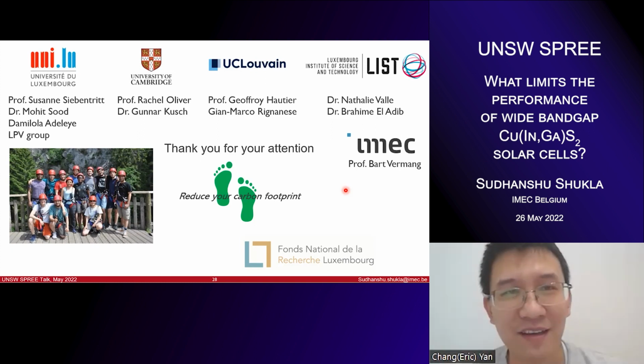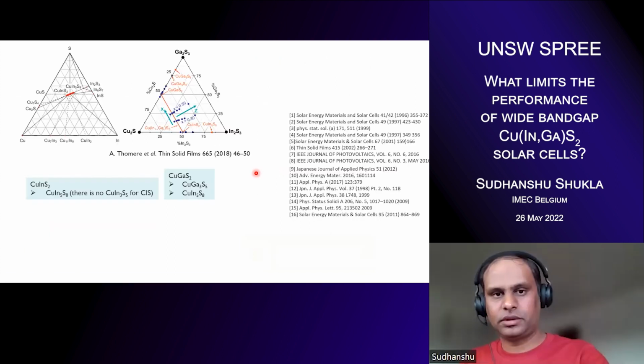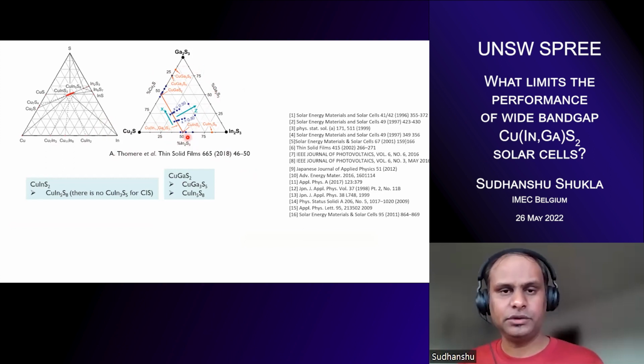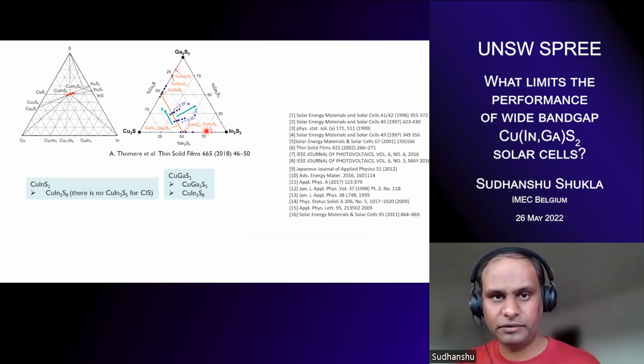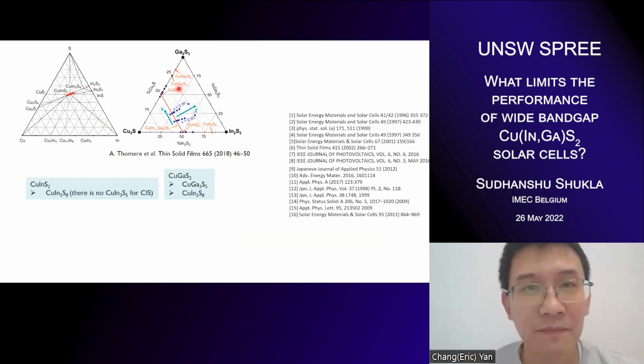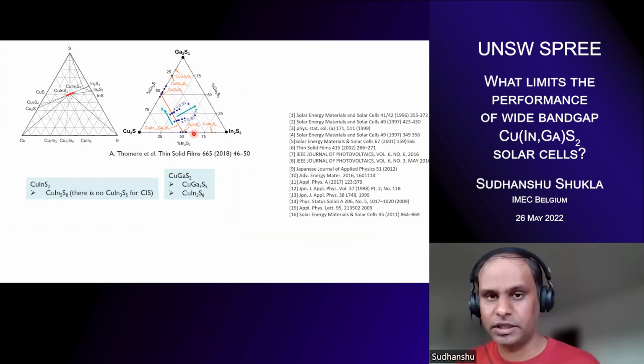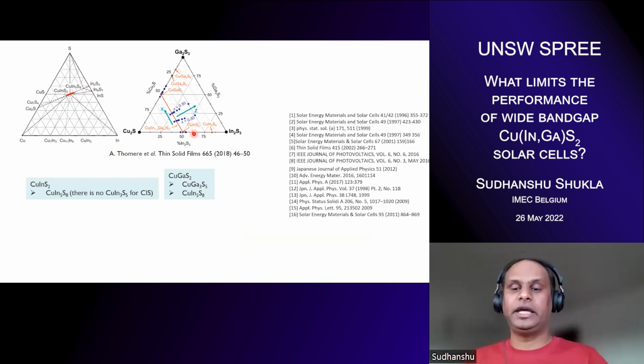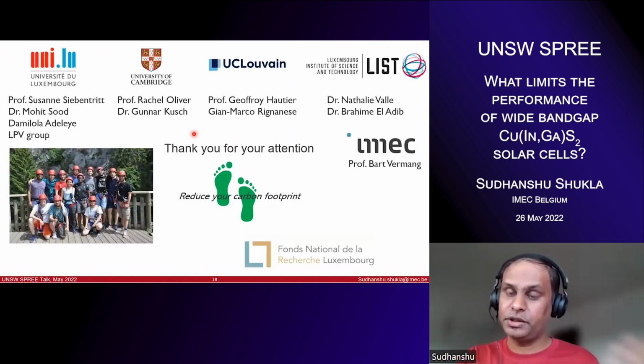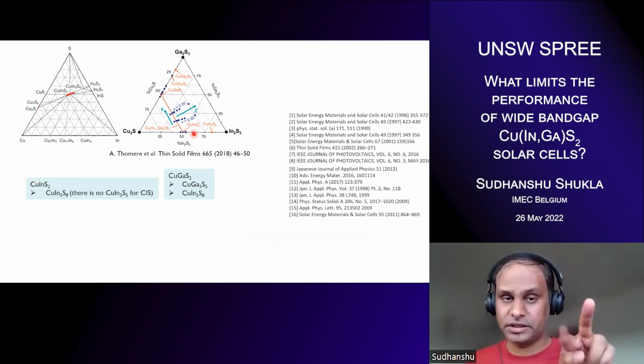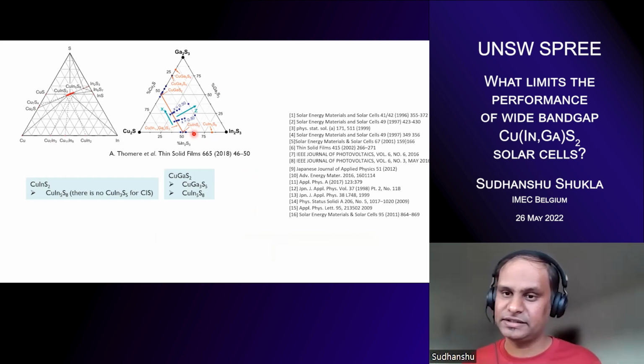Okay, so are you speculating there's some kind of OVC formation at the back that can decrease the fill factor? Yeah, so I have some backup slides here. I think you are familiar with this particular phase diagram, from A. Thomere, which tells you that if you move from the copper sulfide to the indium sulfide line, you do not have the formation of the 1-3-5 compound. You see copper 3-5, but you do not get 1-3-5 formation in the case of indium films. So saying that you have similar OVCs as compared to selenium, I would not say so, because there is something fundamentally different when you compare selenides and sulfides.